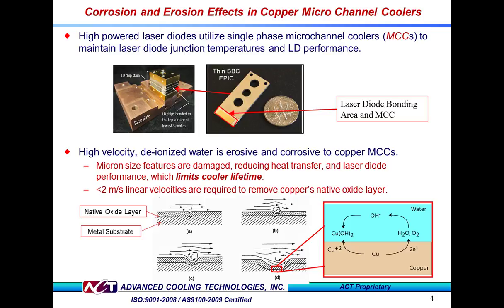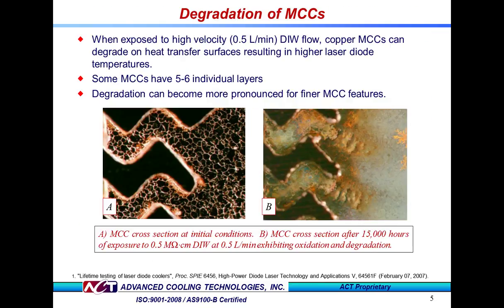Simultaneously, flow rates with linear velocities of greater than 2 meters per second can strip the native oxide off the copper surface. Seen in the schematic on the right is the corrosion equation. The presence of bare native copper with water and oxygen causes electrons to separate from the copper. The free electrons combine with the water and oxygen to form a hydroxyl group, which then combines with Cu+2 to form copper hydroxide, which is subsequently converted to the native copper oxide.